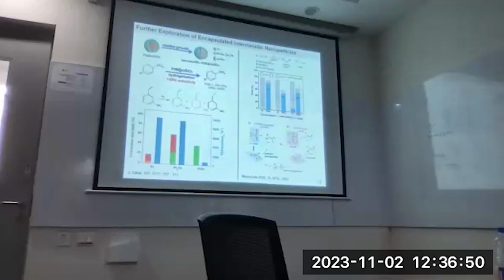So yeah, this is my work in my PhD, and if you see the theme here, mostly I work with precious metals, which is not feasible for large scale. But I could not avoid platinum and palladium wherever I worked. I tried to incorporate some amount of copper and other metals, but I couldn't do it. By the time I finished my PhD, it was mostly palladium and platinum. But when I came to KAUST, first to the applied sciences and then to KAUST, I was only working on non-precious metals like copper, zinc, and then nickel, cobalt. Cobalt is also slightly expensive, but when you alloy it with other metals, it starts to make sense.